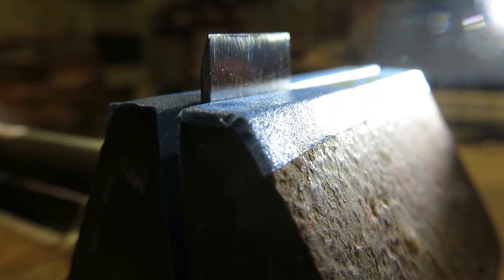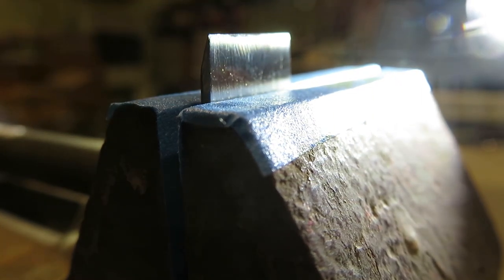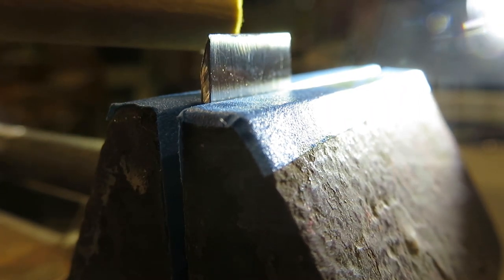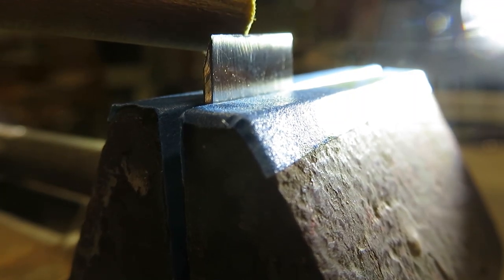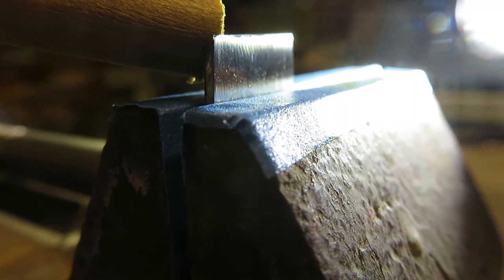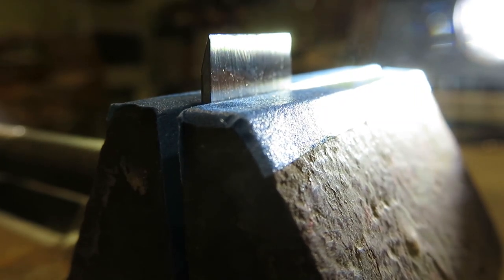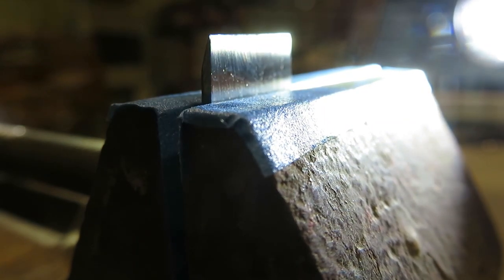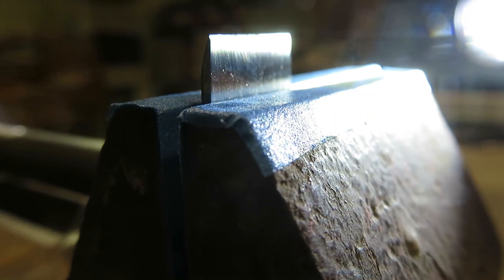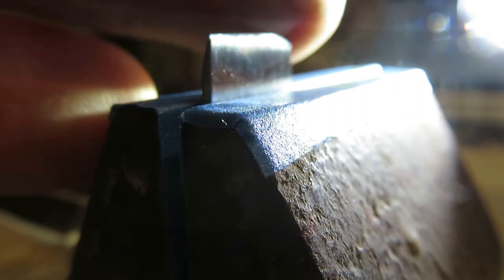I hope we are able to focus on what I'm going to show you here. This is that same O1 tool steel 20-degree single bevel. When the edge is that thin, the side load that I talked about, pushing on it during rotation, is going to impart a lot of forces. Here I've got a wooden dowel. I'm going to push on the edge and you're going to see that edge bends—it yields like aluminum foil. There's just nothing there to back up the forces. You see how it's bending?